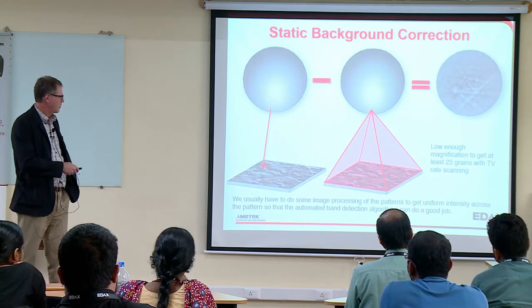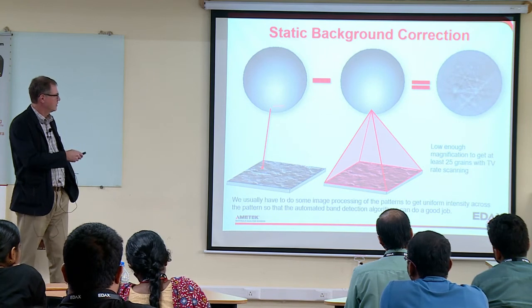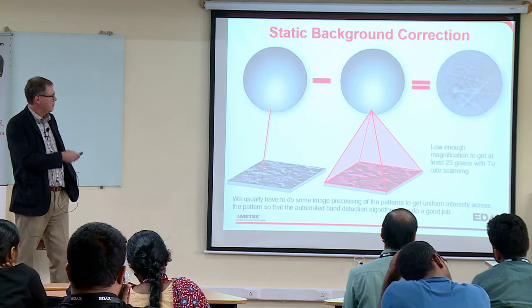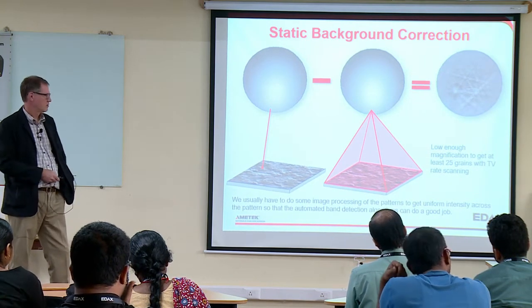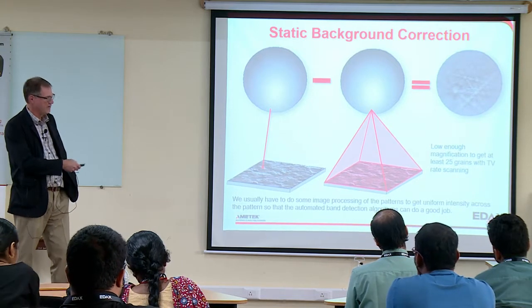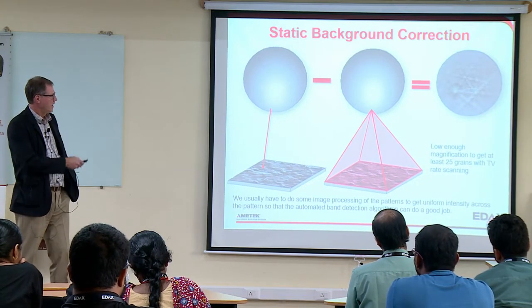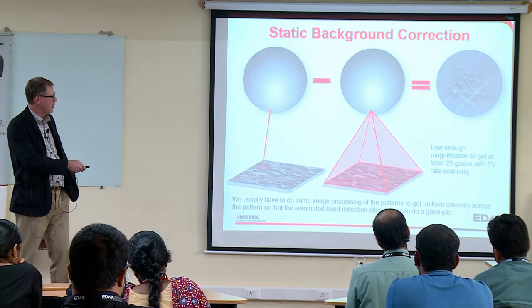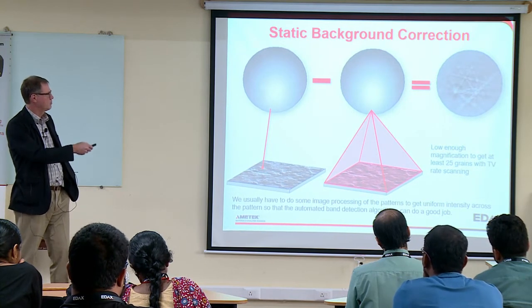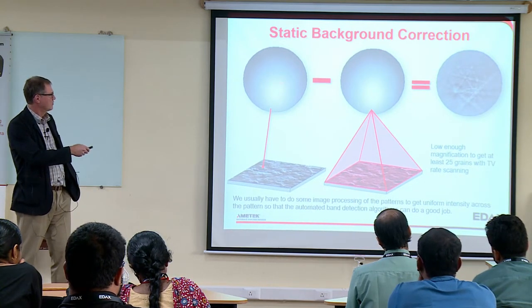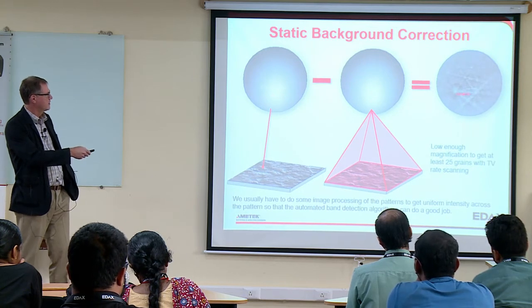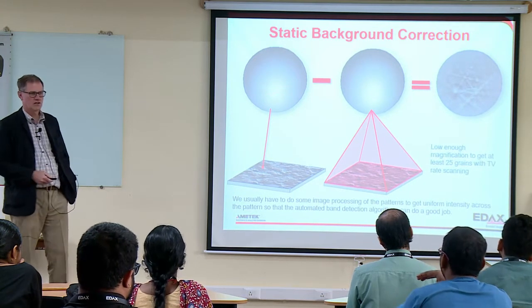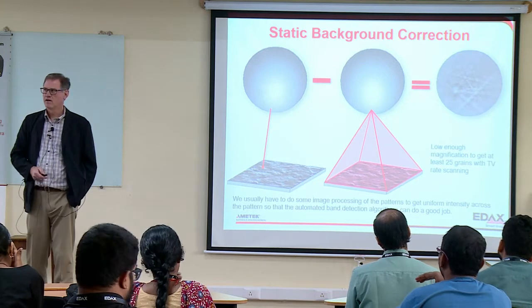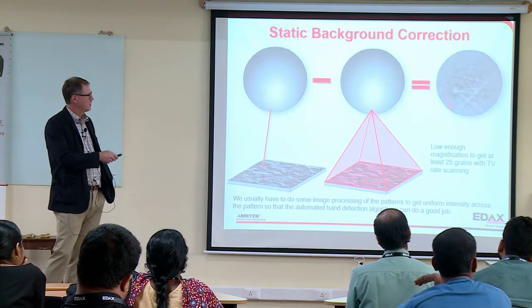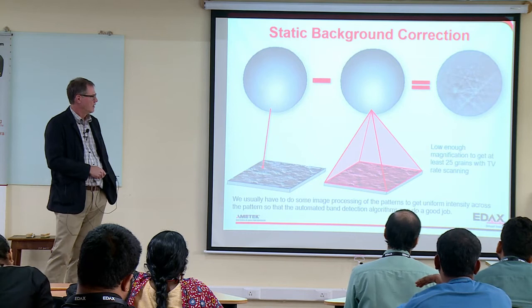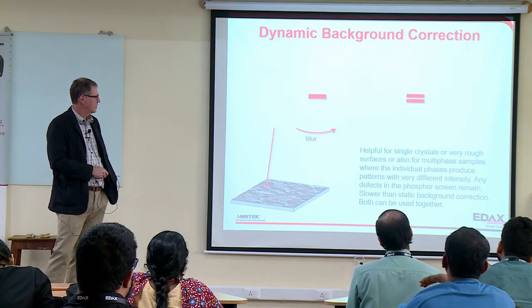The idea here is you get a pattern from a single grain, an individual grain, and you get a background from very many grains. So something like 25, actually about 500 would be really good. And what you then end up with is the average pattern over all these grains, which is just a smooth background. And so now you're able to subtract that from this, and you're able to flatten this intensity gradient across the pattern and homogenize it. And you're able to get this kind of pattern here. And with that, then, we can start to do some indexing.